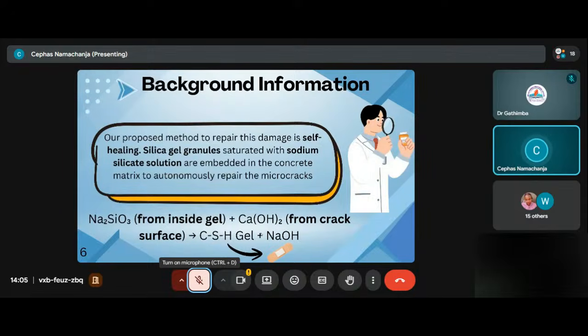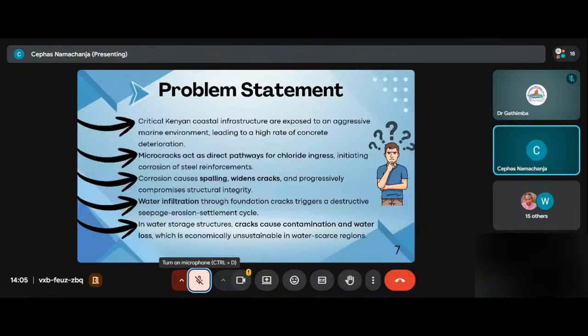It will involve saturating silica gel granules, our carrier, with sodium silicate and placing them in the concrete. The reaction between sodium silicate and calcium hydroxide will yield calcium silicate hydrate gel, which will act as the sealant for our cracks. So for our problem statement, microcracks act as direct pathways for chloride ingress.